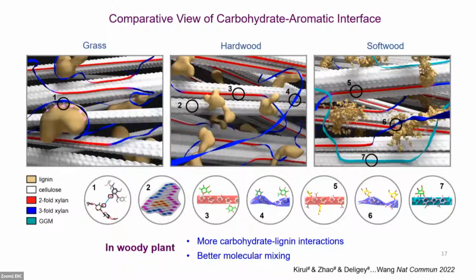Now we can wrap up all the NMR findings to give this illustration model to show all the major findings. In the hardwood and softwood, we can see the lignin to cellulose contact, and in the wood samples, there are more carbohydrate and lignin interactions, and there's better molecular mixing when compared to the grass model.